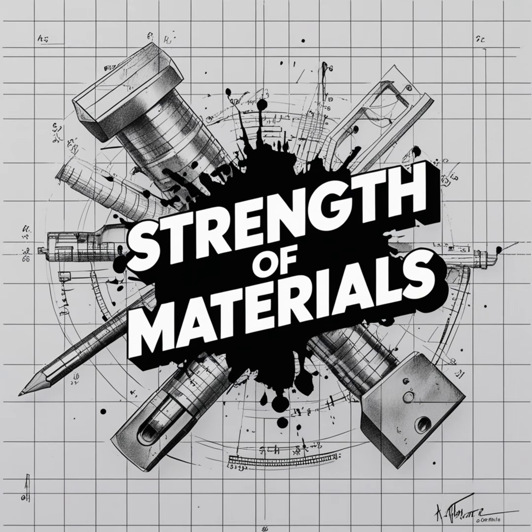Increasing the strain rate, meaning you apply the physical load very suddenly, increases the transition temperature, pushing the material toward brittle behavior. Okay, so faster impact equals more brittle. Exactly. If we connect this back to our traffic jam analogy, it makes perfect sense. Ductile behavior requires those dislocations, those crystal defects, to physically slide and move through the metal to relieve the stress. Right, the cars need time to merge into the shoulder. Yes, that atomic sliding is a physical process, and it requires time to happen.